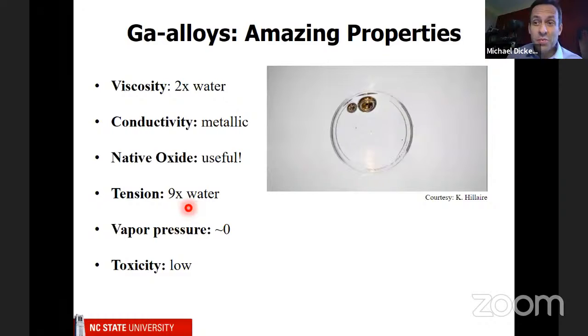So the most important point from this slide is that it reacts with air and forms a very thin oxide layer. It's about 3 nanometers thick. And that has a big, profound effect on its behavior, and I'll show you in just a moment. Another interesting thing, it's got zero vapor pressure. That means, so I have some water here, and water has a vapor pressure. So if I leave this cup here, it's going to eventually evaporate. This has no vapor pressure, so it will not evaporate. So you don't have to worry about breathing it.